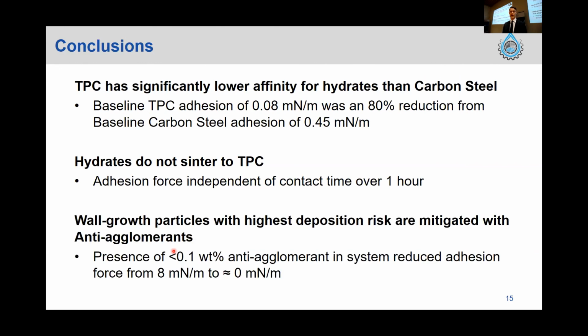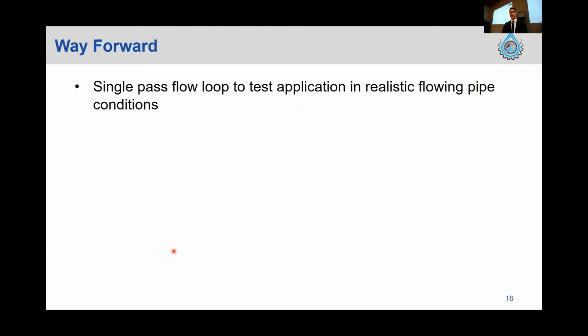And lastly, to recap, the wall growth particles, obviously with that 100-fold increase in adhesion force, were shown as being the most problematic and highest risk, and those could be mitigated quite well with the presence of a low weight percent of anti-agglomerants. And some of the points for the way forward from this: I think it would be quite advantageous to test this material at some point in a single pass flow loop under more continuous and realistic conditions to see how it holds up with hydrates.